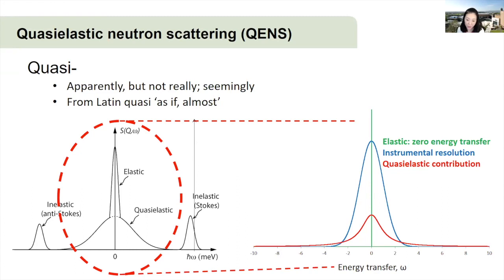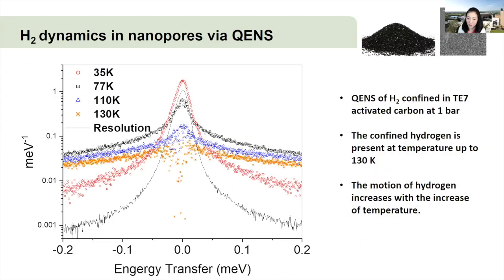And compared to INS, QENS offers much higher resolution, which gives the opportunity to quantify the hydrogen dynamics, to quantify the mobile and the immobile phases of confined hydrogen. So we carried out QENS on hydrogen confined in TE7 carbon at 1 bar across different temperatures, and the black peak is the instrument resolution. If all hydrogen were completely immobilized, there would not be any broadening, so we would only see an increase in intensity. But at 35 Kelvin, the red circles, we see the hydrogen molecules are moving in a confined geometry, reflected in a broadening of the peak.